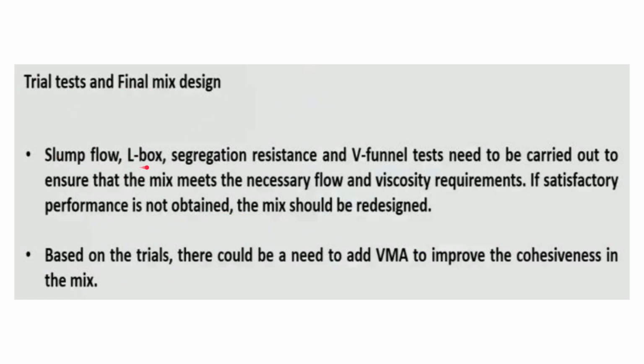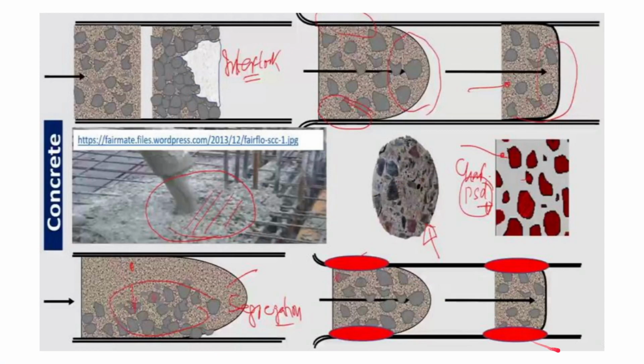Slump flow, L box, segregation resistance and V funnel tests need to be carried out to ensure that the mix meets the necessary flow and viscosity requirements for SCC. If satisfactory performance is not obtained, the mix should be redesigned. That is a basic norm. Based on the trials, there could be a need to add VMA to improve the cohesiveness of the mix. For cohesiveness we have to add VMA, and for other requirements we can go for superplasticizer and powder addition. Through this we can take care of the issues which we have discussed here.